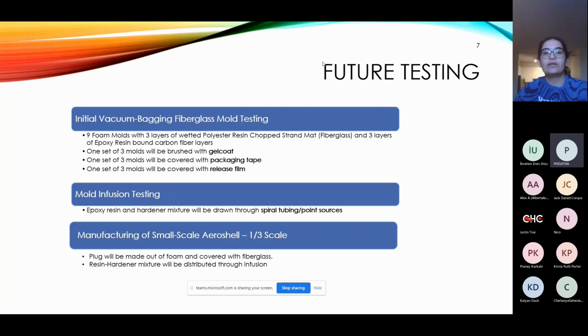The 3rd test will be the manufacturing of the small-scale aeroshell, which is 1/3 of the scale, where the plug will be made out of foam covered with fiberglass, and the distribution of the resin hardener mixture throughout the mold will be through infusion. From the results of the previous tests, the manufacturing of the large-scale aeroshell will be optimized accordingly.